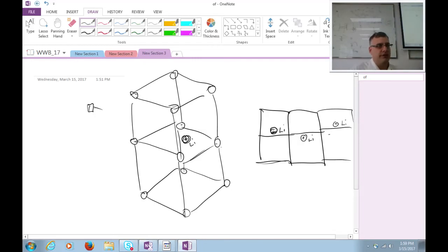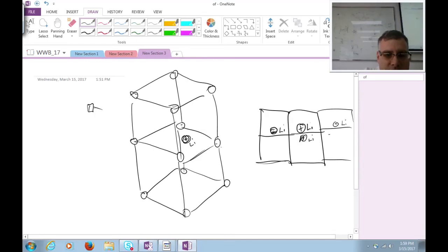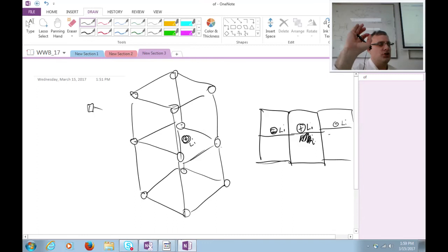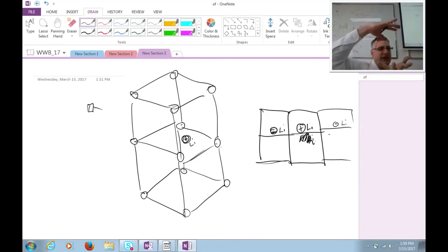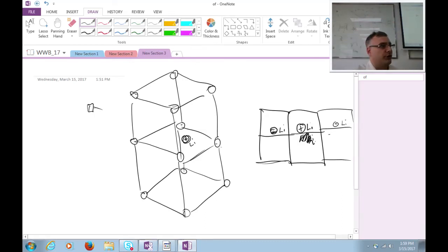However, if you pole the device, that is, you take this material and heat it up, the Lis are bouncing back and forth, you don't know which side they're going to end up, but you apply an electric field and then you cool it down. The electric field will push all of them mostly to one side while they are hot, and then when they cool down, they all stay on the same side. What this will do is break the inversion symmetry on average for this repeating unit. Now if you compress the device, the substrate, you'll get that same electric dipole moment that's proportional to force and accumulates through the medium.